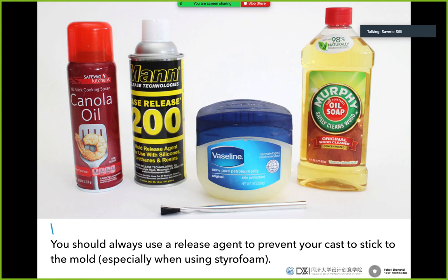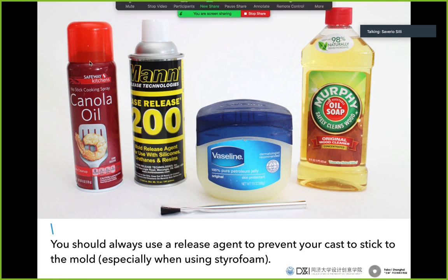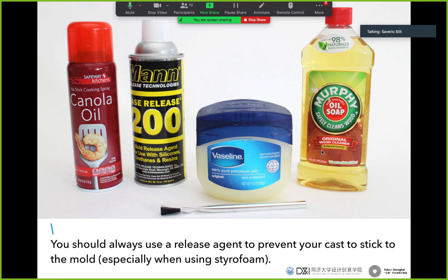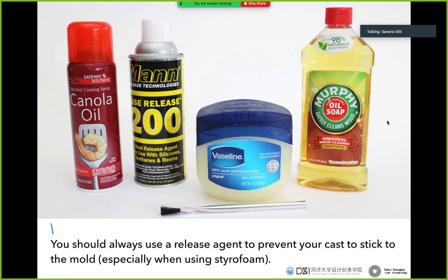Release agents can go from the more professional ones, like Ease Release, to oil, Vaseline, or another kind of oil soap, and so on. You need to know what material you are using, and whether your material works well with the release agent. For example, if you are using any polyurethane, you can never let polyurethane come into contact with anything containing water. Otherwise, you will have a nasty reaction.